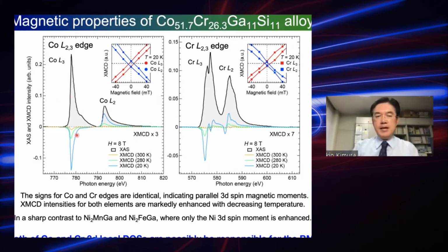And also the XMCD intensities grow very rapidly with decreasing temperature. This is similar to what we observed for the Ni2MnGa and Ni2FeGa shape memory alloy films. However, in this case, both elements show a similar behavior. This indicates that both the cobalt and chromium 3D local densities of states possibly are responsible for the reentrant Martensitic phase transition.